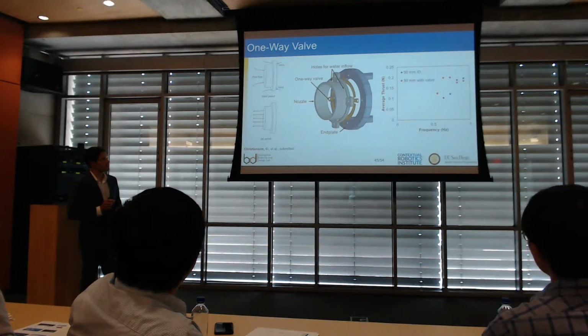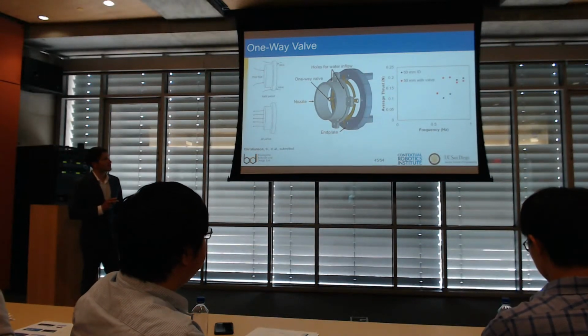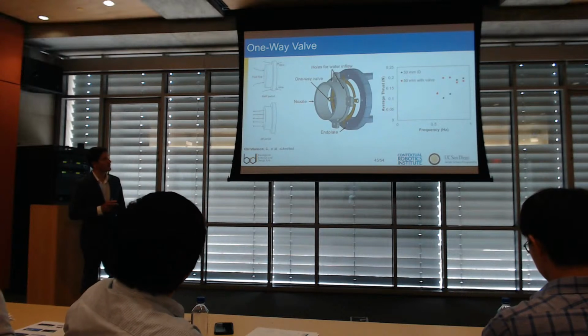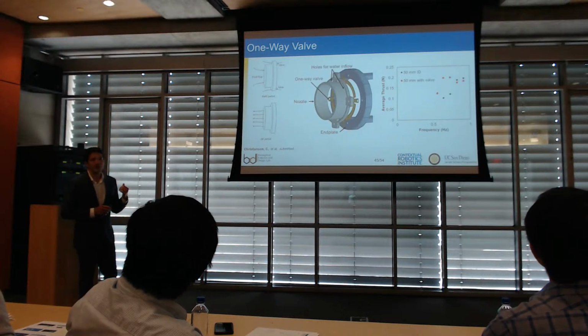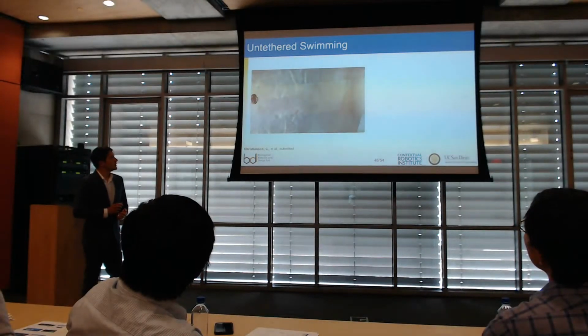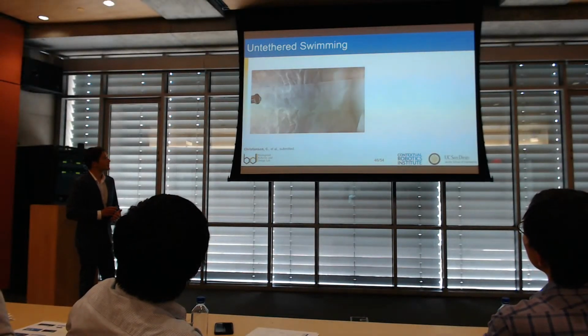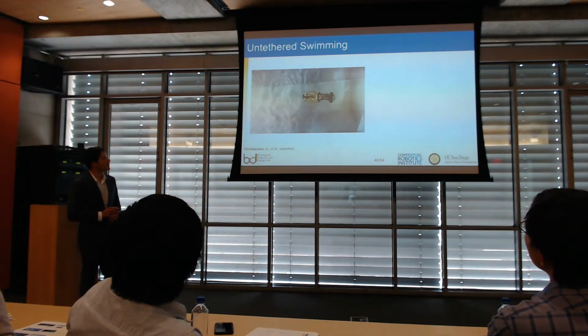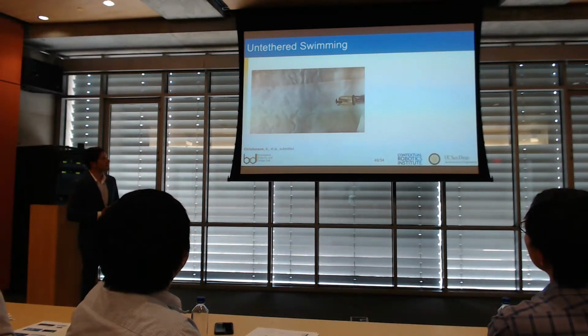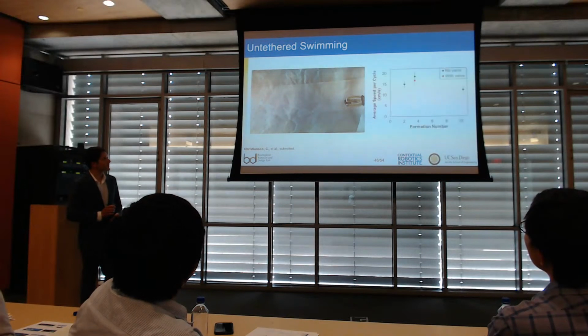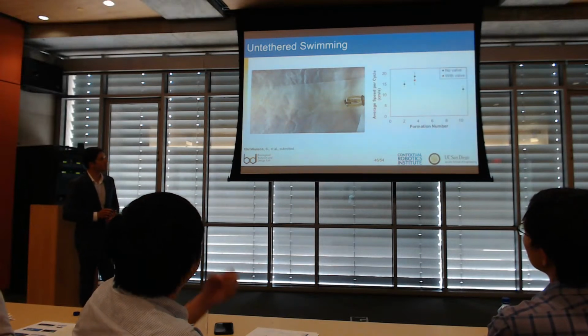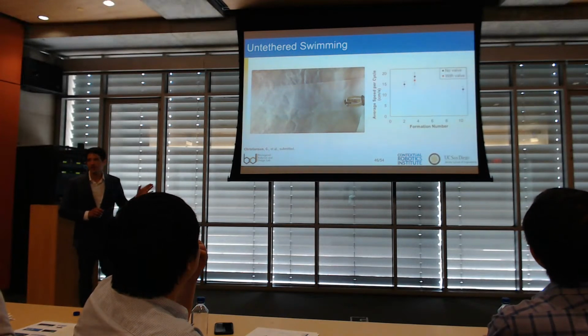With the valve, it was similar to without the valve at high frequencies, but we had better performance at some of the lower frequencies. So here's a video of untethered swimming. We have the waterproof power supply on the front of it, and it's swimming through the water. And then we can measure the average speed per cycle as a function of formation number.